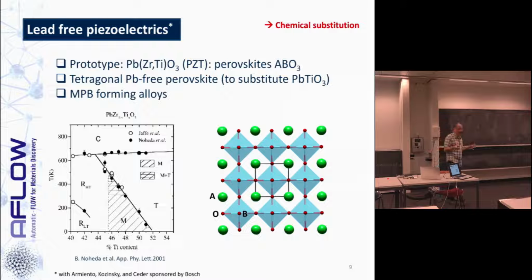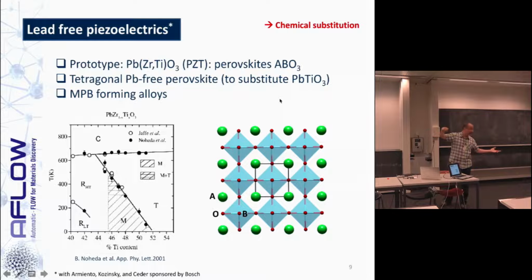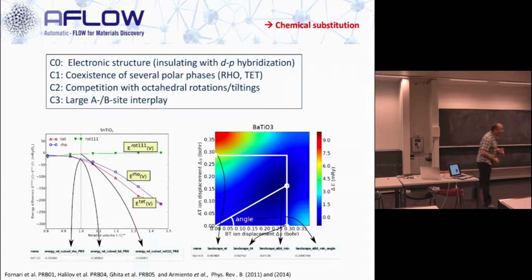These are two slightly different goals, right? And in the perovskite structure, what we did is, as a start, we take the ABO3 structure, supercells of it, and we start populating with all the possible A and B. We kept only oxygen. Okay, so we had almost 4,000 calculations, and once we did all these calculations, we tried to distill whether we can find something new that exhibits the same property of PZT without containing lead. Okay, so how could we look at that?